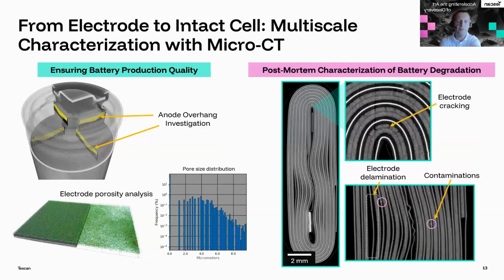When studying the quality of assembled cells, micro-CT is extremely valuable because it enables non-destructive imaging of all internal components. This technique helps ensure battery safety by analyzing anode overhang, identifying contaminations, and it also supports performance evaluations through the study of the electrode porosity and material distribution. In failure analysis laboratories, micro-CT is used to investigate battery damage such as electrode delamination and cracking, and moreover, it allows in situ studies of internal battery processes during cycling and under specific environmental conditions.